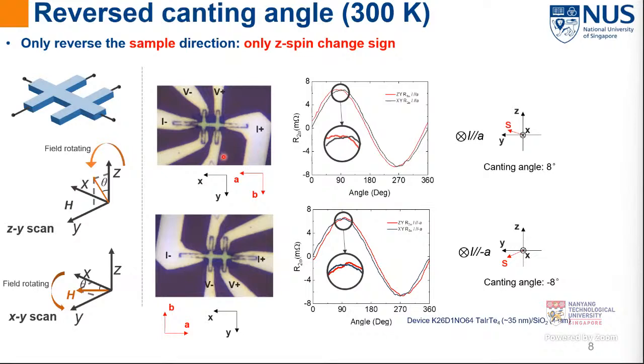Next, we perform another experiment in which we rotate the sample by 180 degrees, but keep the current flowing direction and magnetic field rotation direction the same, which means that now we are flowing current from the A-axis to minus A-axis. In this case, it can be seen that the Z-spin canting direction has changed from plus 8 degrees to minus 8 degrees. However, this angle is very small. It's only 8 degrees, which could also be accidentally induced by the error bar.